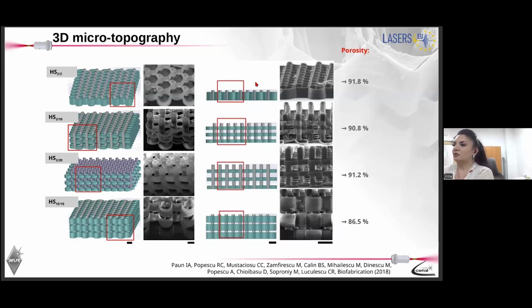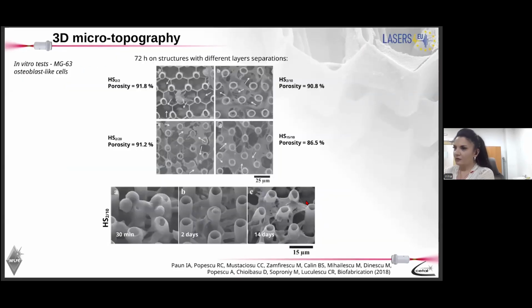Based on the simulation of the structure, we were able to calculate the porosity for each of these arrangements of the layers. And we cultivated cells on each of the structures. We saw that the worst case scenario is here, where we have no spaces between the layers. The cells go inside each round hexagonal shape here, but they are separated. They do not interconnect, and as a consequence, they die. The best case scenario is here, where the cells attach not only on the surface, but also appear to form some networks inside the structure.